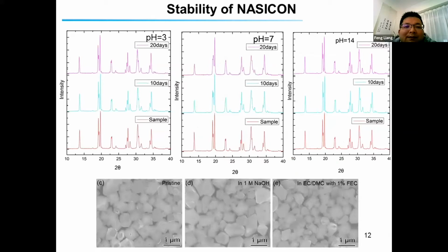And also we investigated the stability of this NASICON structured solid electrolyte. Because this solid electrolyte should be immersed in the aqueous electrolyte, we checked the stability of this electrolyte in the aqueous electrolyte with different pH values. Also, we checked the SEM of the solid electrolyte in the organic electrolyte. Both of these results demonstrate that the solid-state electrolyte has a good stability.